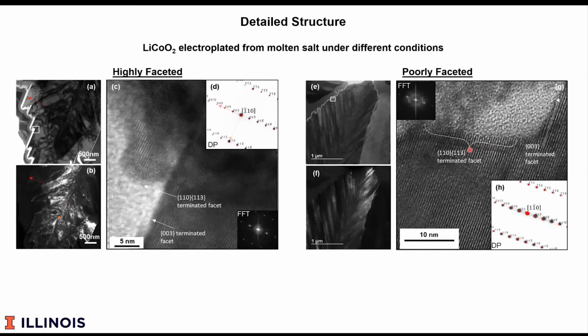Here is some high-resolution electron microscopy so you can see a little bit better. This is the highly faceted material you're looking at. Remember, there were those 003 planes. Here's a 003 terminated facet, and here is a mix of 110 and 113. The lithium goes in and out of the planes this way, and so when lithium hits a 003, it's largely blocked. In the poorly faceted, it's superficially similar. There's a much higher step density, and now the faceting isn't as sharp. This probably leads to more interfacial reactions, but that's just a hypothesis at this point. These are things that one can control by controlling the chemistry of the system.